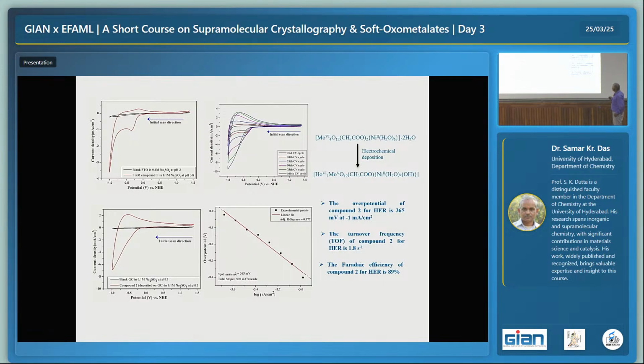It is not MoO3 but a molybdenum bronze. It is now mixed valence, and the color was different. Now it became a very shiny lustrous color. So it is a molybdenum bronze intercalating a nickel aqua hydroxy compound. This is the compound we characterized by different studies. It took 6 months to characterize because we don't get a single crystal structure of this deposited material. Then we did all sorts of characterization, and we could get all the parameters.